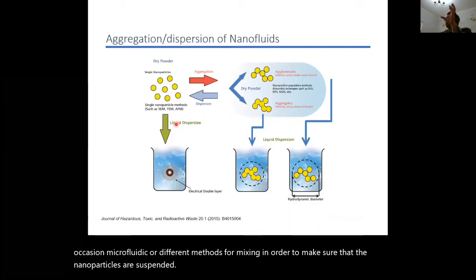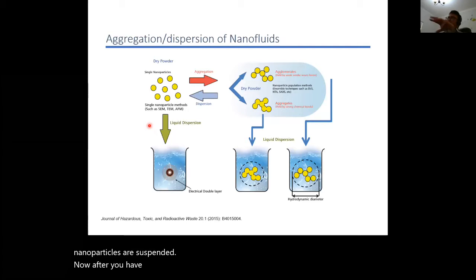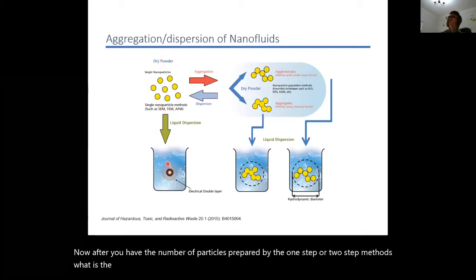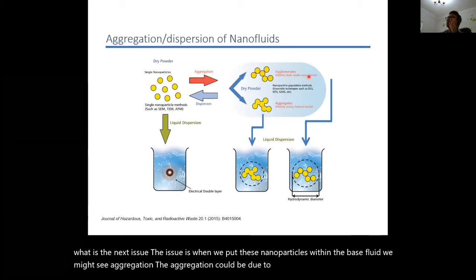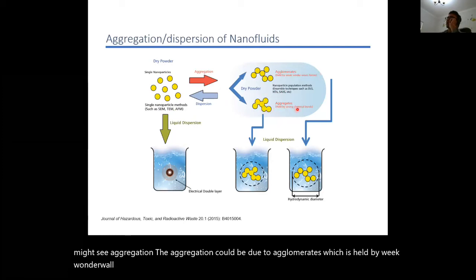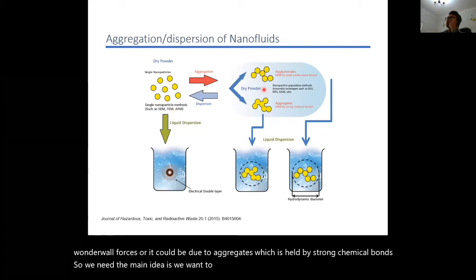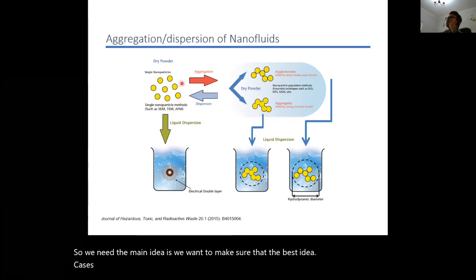Now, after you have the nanoparticles prepared by the one-step or two-step methods, what is the next issue? The issue is that when we put these nanoparticles within the base fluid, we might see aggregation. The aggregation could be due to agglomerates, which are held by weak van der Waals forces, or due to aggregates, which are held by strong chemical bonds. The ideal case is to have each nanoparticle suspended alone, but that does not happen. Usually you'll have two or three particles coming together when you suspend them in a fluid.